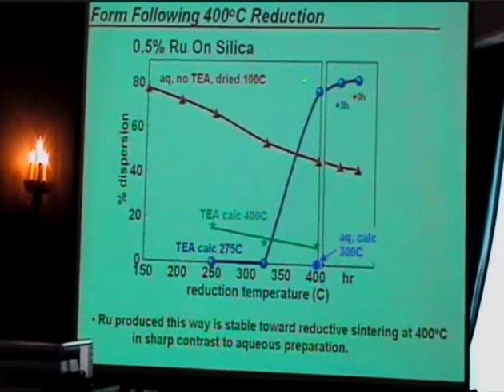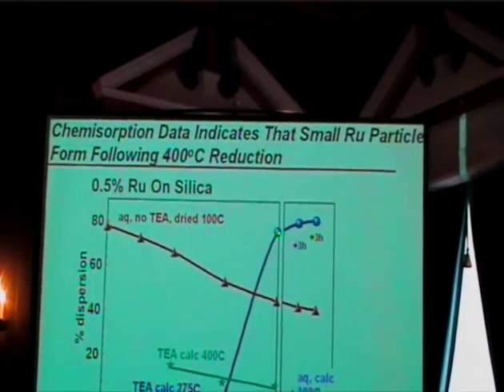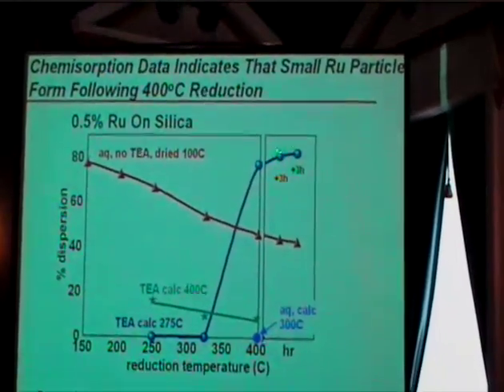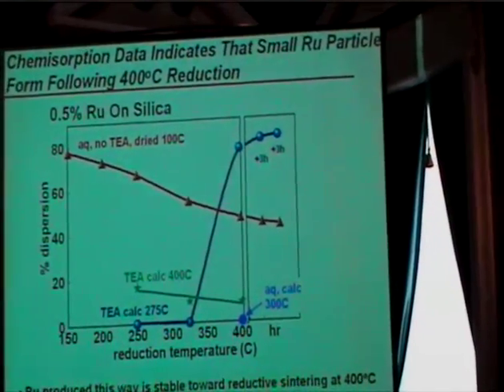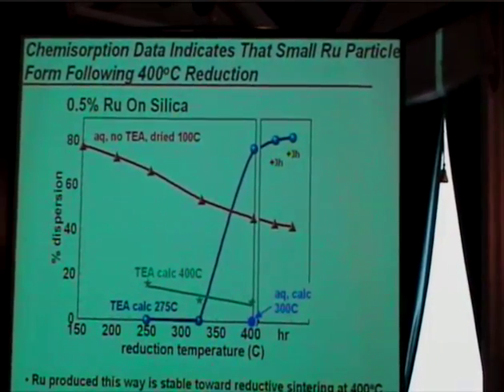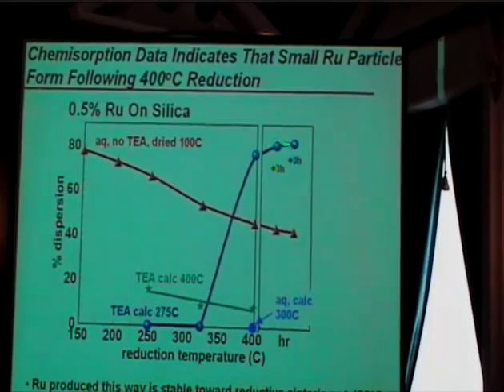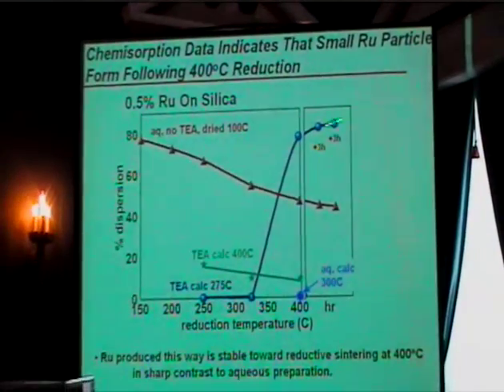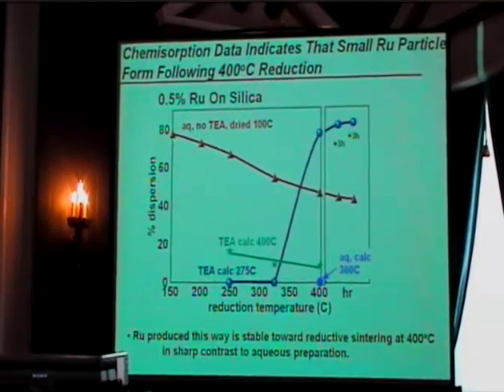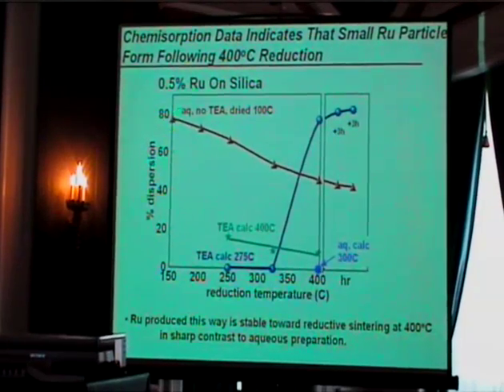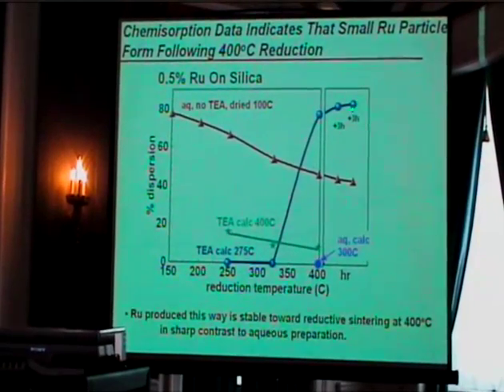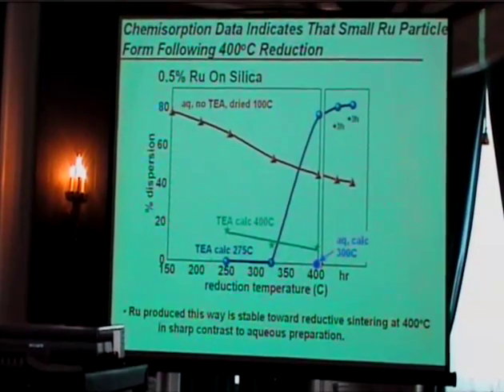But notice that when we go ahead and further reduce this for 3 hours further and measure chemisorption, and then another 3 hours measure chemisorption, the values stay very stable. They don't go down. In fact, even go up a little bit. Okay? So, whereas you can say, well, I have an 80% dispersed catalyst here, I have an 80% dispersed catalyst here, they're not the same things. Okay? Something different has happened, and that's what I was referring to in the beginning.